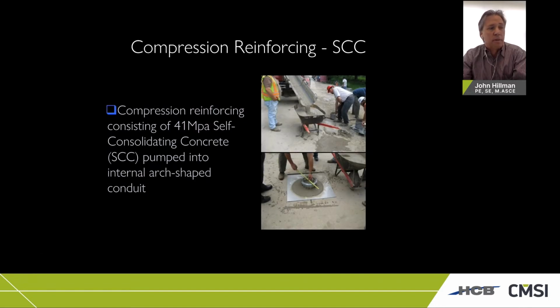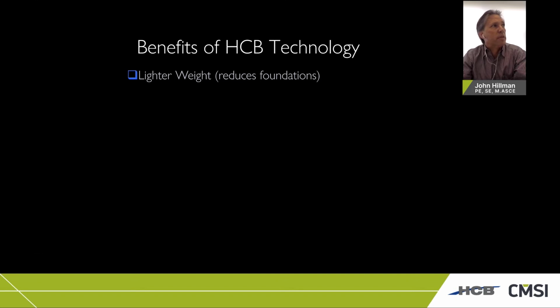The concrete we use is nothing special, just a 41 MPa self-consolidating concrete that's overdosed with super plasticizers and viscosity modifiers, so it flows out like water. I'll show you a little bit more about how we fill this later, but with the SCC, you do a J-ring test instead of a slump test, because you basically want it to be able to flow through the beams and fill all the voids. So the benefits of this technology, obviously you get the lighter weight, so you've got reduced foundation costs. It's usually the mass of an HCB is about the same as a steel beam when they're all said and done.